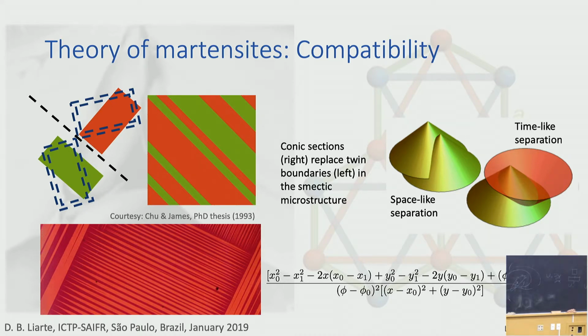And I'm showing here two different cases. One where the two cones have the same sign, a plus sign, for instance. If you look at this figure, you can convince yourself that the intersection between the two cones will look pretty much like a hyperbola. And in the other case, if you have a plus and a minus sign, the intersection will form an ellipse. And you can derive the intersection based on the parameters of the translation group of symmetry. And this is the equation. You don't have to pay too much attention to it. But it describes these compatibility conditions and it generalizes the twin boundary compatibility conditions in the Martensite case.